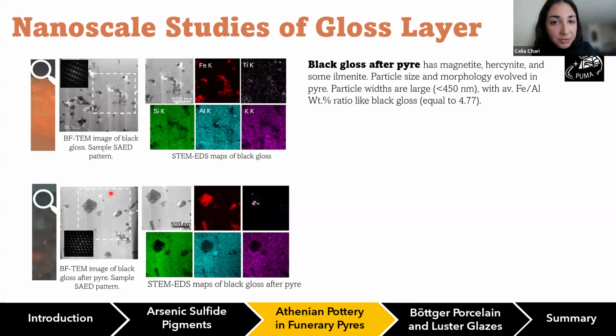The black gloss after the pyre has magnetite, hercynite, and also ilmenite. Ilmenite was not something that we found with the earlier samples, also because we did not have an ilmenite reference in our studies. So this was a new observation. And this is actually similar to what we saw with the black gloss on the red ceramic. In both cases, we're seeing magnetite, hercynite, and some ilmenite.